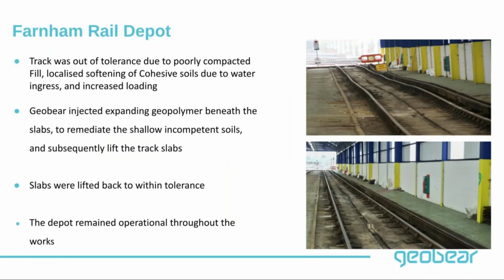And actually, this was not the final case study. This is actually the final case study, in Farnham Rail Depot. The depot was experiencing significant differential settlement on the track, and the picture tells you how it looked before we were commissioned to do any work. It had very poor geometry, and this was driven by poorly compacted material underneath the slab in the depot. We were commissioned to come in and carry out our injection, and you can see the post-treatment photo at the lower bottom right hand. You can see a significant improvement of the geometry. You can visibly see that.